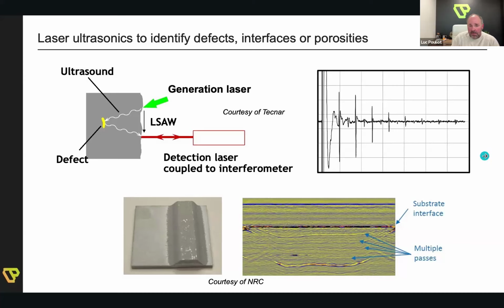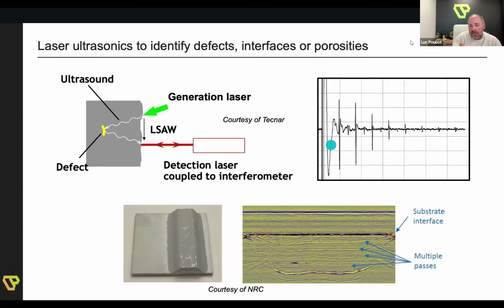So what you see on the top of the screen is a schematic that allows us to explain the principle. The hammer in this case is a very short pulse, high intensity laser, typically generating megawatts, but over 30 or 40 nanoseconds. That generation laser will induce a plasma at the surface, and that plasma will generate in turn surface and bulk acoustic waves. We're interested here in the bulk acoustic wave traveling towards whatever type of defect or interface there is in your coating or buildup. What you obtain using the detection system, another type of laser, long pulse in that case, coupled to an interferometer, is the kind of echoes that you see on the right-hand side.